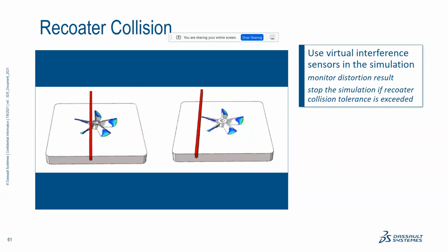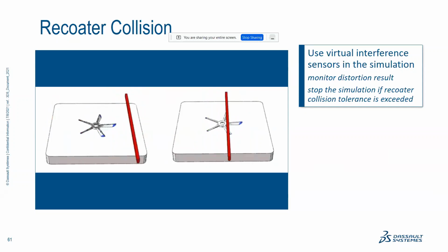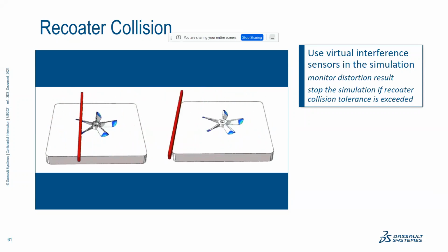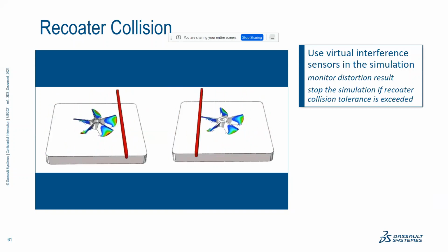So as the part is warping, it affects or interferes with the recoater, which is depositing the powder and flattening it out. So in that way, the part which was underlying it warps and comes and hits the recoater blade, which can either damage the part or it can damage even the recoater and so on. So to reduce this impact, we can even represent that through sensors in our recoater collision capability.